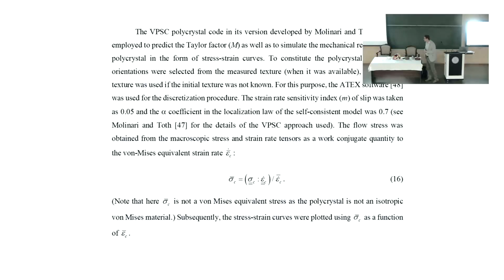So what can be used instead? Actually, what can be used instead is the so-called work equivalent stress. So epsilon dot is the von Mises strain rate. It's accepted, right? Now we want to define the equivalent stress scalar. The problem is just this. When we do a testing, strain hardening, we are measuring scalar values, and we want to get the same scalar values from the simulation as well. But in the simulation, of course, there is a strain rate tensor, there is a stress tensor, nine components.